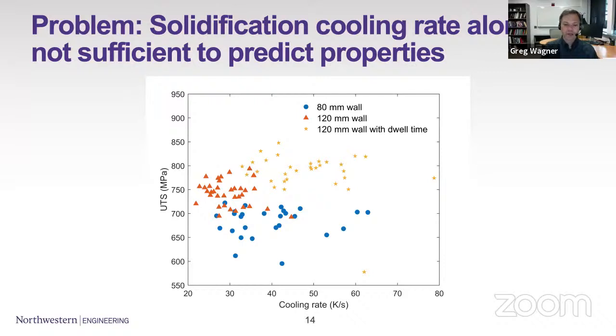So the cooling rate versus UTS here, these are the three different walls, three different wall cases. What we would hope to see here is that we could plot a trend line and at least, up to some kind of uncertainty, be able to see a slope in this data. But that slope is just really not there. And I think the relationship between cooling rate alone and UTS is not so clear. So this was sort of disappointing. So clearly, though, there's something about the temperature history that is affecting the properties, and we want to be able to look in a little bit more detail.